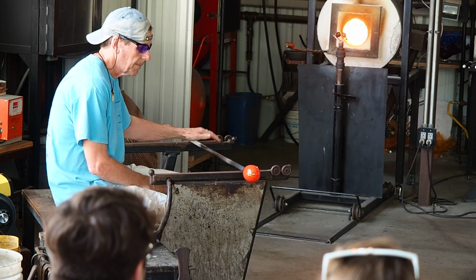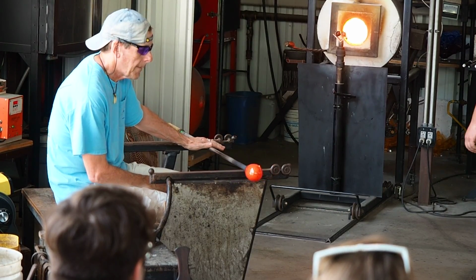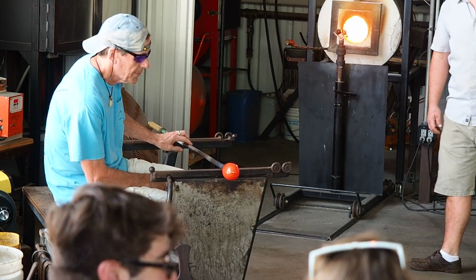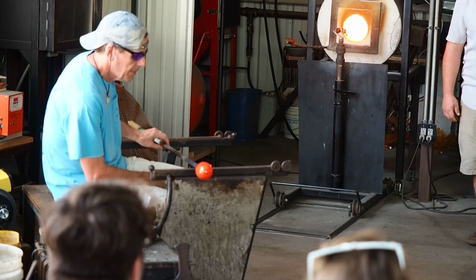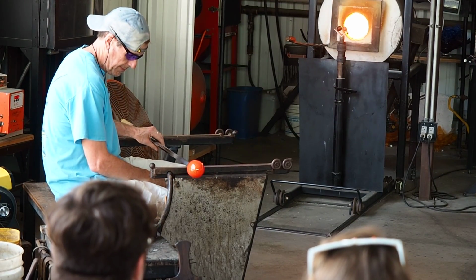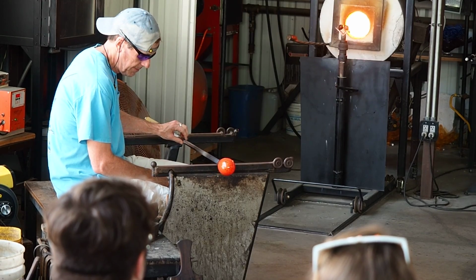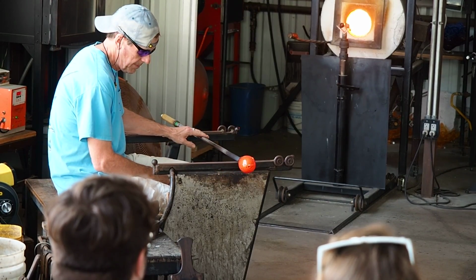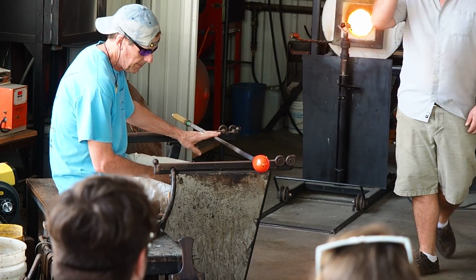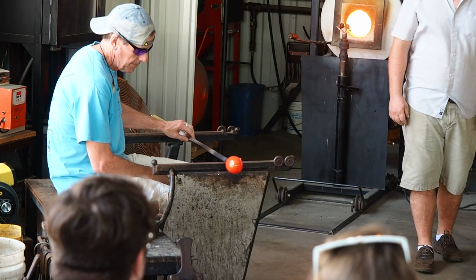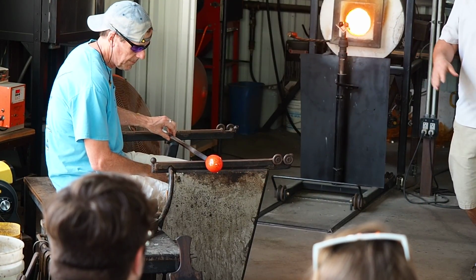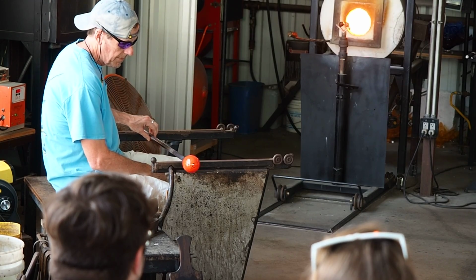These will indicate to Paulie that he's right around 1,000 degrees, which is relatively cool in terms of glass blowing. It'll also tell him that the glass is set up and it's nice and stiff and will support that next gather. If you went in too early and that ball of glass was too soft, you could potentially collapse the bubble as the weight of the surrounding melt surrounds it.